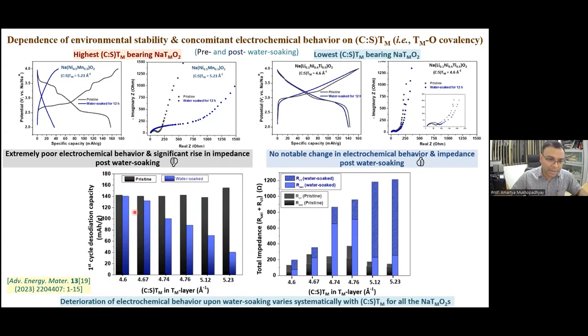The details of all these are in this paper, so for the sake of time, I cannot talk about all the material. Now, if we look at the impedance, again, with increasing charge to size ratio, the increment in impedance between the pristine condition and the water soaked condition keeps increasing drastically. We can see that the charge transfer resistance increases drastically upon water soaking for these unstable materials, which means it is the deterioration of the structure which is the main cause for the rise in impedance and not just formation of surface layers.